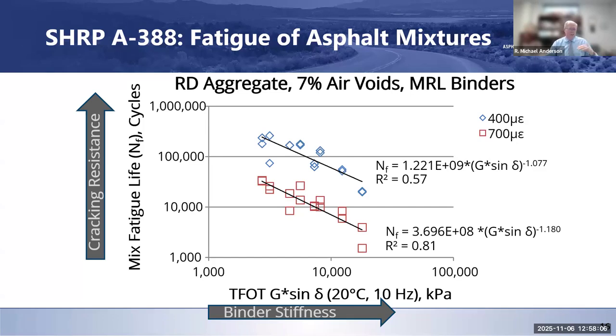So part of the challenge with constructing material out there is that if you put the mix down and you don't roll it very well, it's got more than 10% air voids in it when you're done. Then it's kind of a two-factor thing. First of all, the mix isn't as stiff as it could be, but then you're allowing oxygen to get into it more easily, and so it's oxidizing and getting stiffer overall as it ages, and it's losing its viscoelastic nature. So now you've got a material that has become stiff because of this permeability, allowing it to oxidize like it does. If you can reduce the oxidation that occurs, that can help overall with how your asphalt binder is going to stiffen up and how the mixture itself is going to stiffen up.